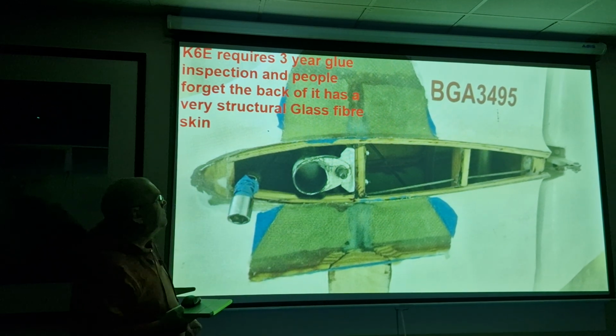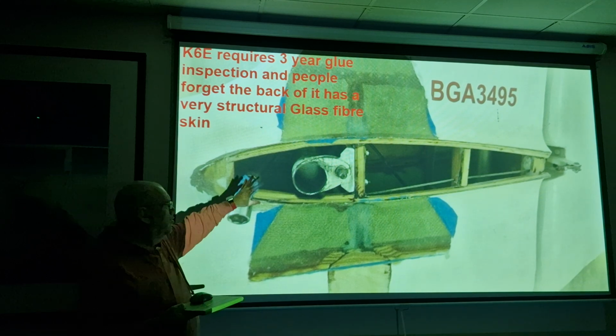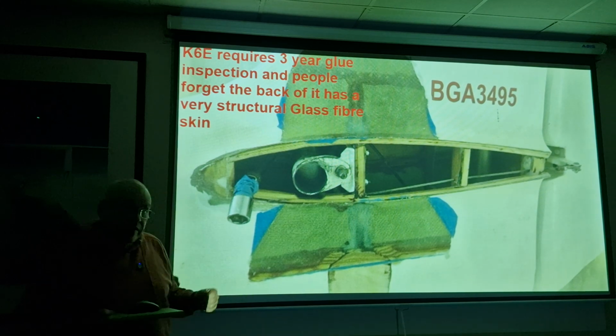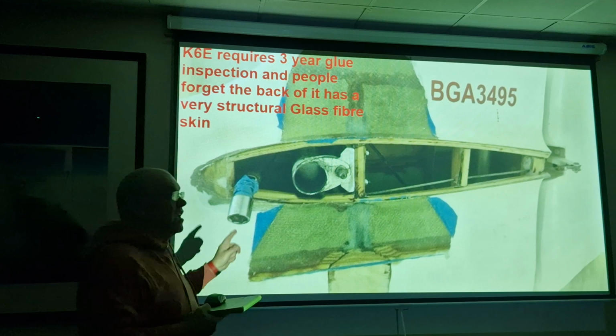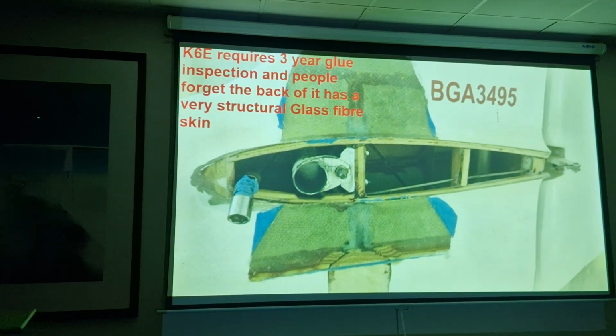So, and then once you've done it, you've got to cook the whole lot at 54 degrees centigrade for 15 hours. But that's principally for the glass fibre. The glue's a lot more forgiving.